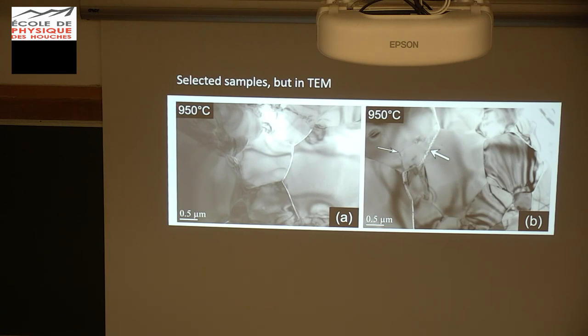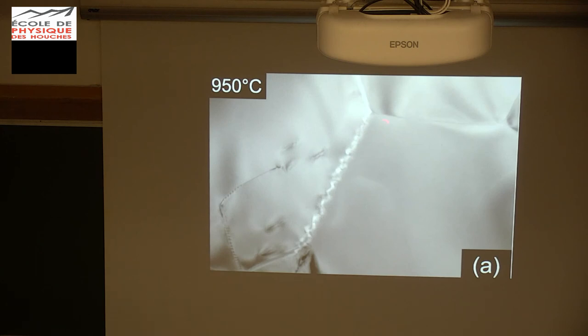Going back to a presentation at the lower temperature — 950 degrees Celsius — you have nice grains, very nice almost straight grain boundaries, but they are open, they are cracked. Some of them remain closed, and some are already open. We have this one with a sort of peaks — asperities, decoration cells — and we're still fighting with each other about what to call that. So we zoom in: closed, tight grain boundaries coexisting with open grain boundaries and some steps. But if I say steps, you might think it's already disconnected — maybe not. It's opening in a weird way, and it coexists with dislocations. So it's not only cracking at the grain boundaries.